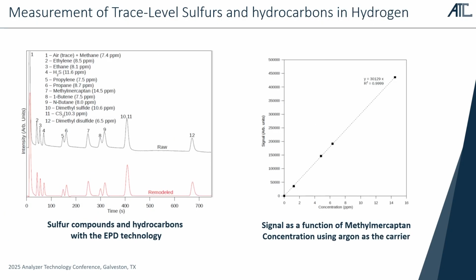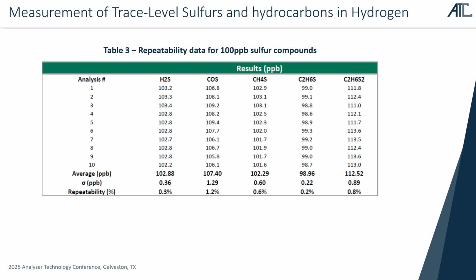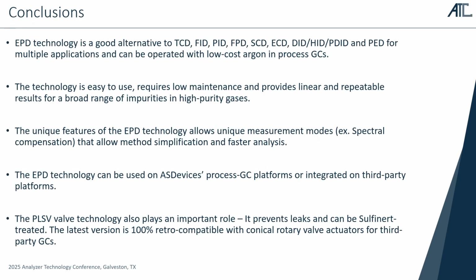Here, another chromatogram with a mixture of sulfur compounds and light hydrocarbons, and just a graph that shows that in the case of methyl mercaptan and all the other sulfur compounds, we have a linear and repeatable response at the ppb level for all the sulfur compounds that were tested.